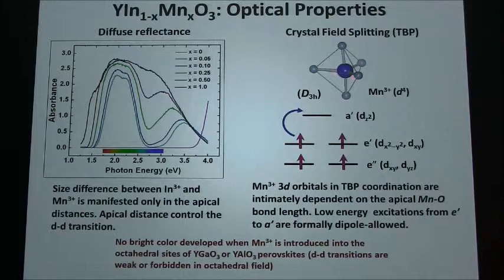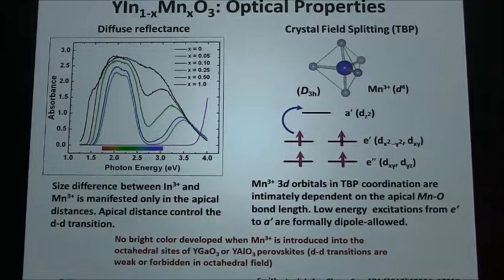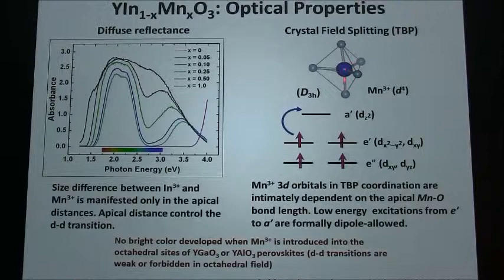because the manganese sits in a five-fold coordination site, it gives enough energy to transfer the electrons within the manganese electronic levels, which is shown here. That is controlled by the distance between this oxygen and this manganese atom, which is again controlled by the indium being present in the same position as manganese. So we have systematically studied why the blue color comes from this, using theory and also electronic transition calculations. So clearly we understand the five-fold coordination in the crystal structure is responsible for the color.